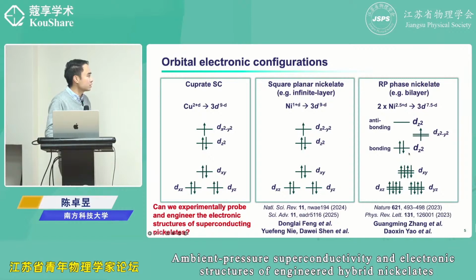And also the important stuff is this dz square orbital because it couples with the pz of the apical oxygen so nicely. So the hopping between these two planes is pretty strong, and then you get a bonding state and anti-bonding state. It's quite well separated, and if you count the number of electrons near Fermi surface, Fermi level, the dx square minus y square is still there, but this dz square is very close to the Fermi level. So the question we want to ask is, can we experimentally probe and also engineer the electronic structures of the superconducting nickelates?